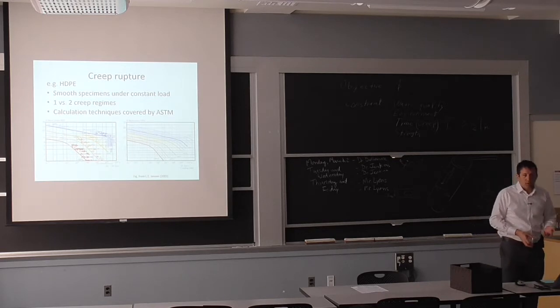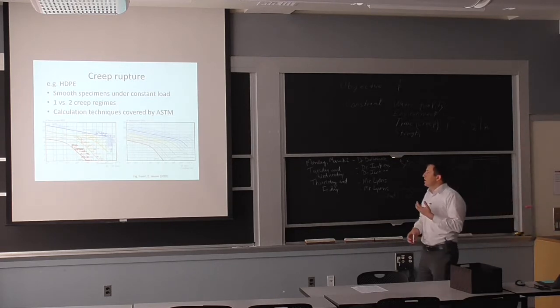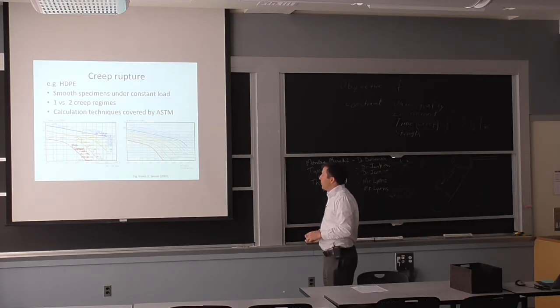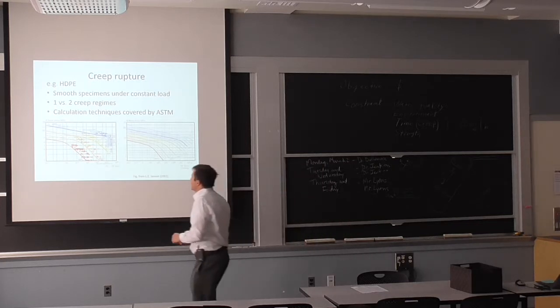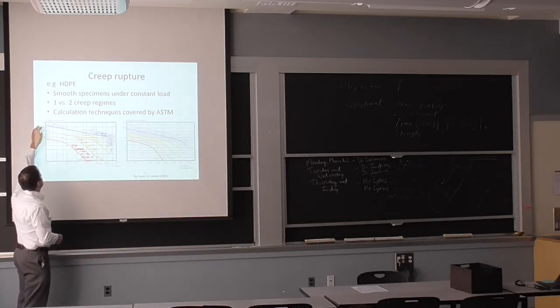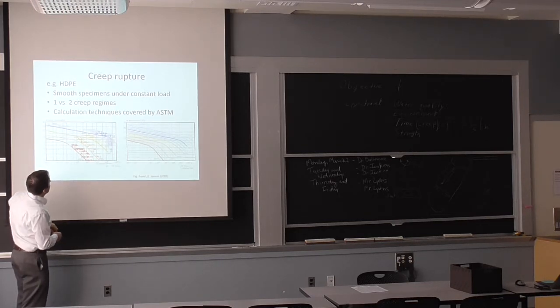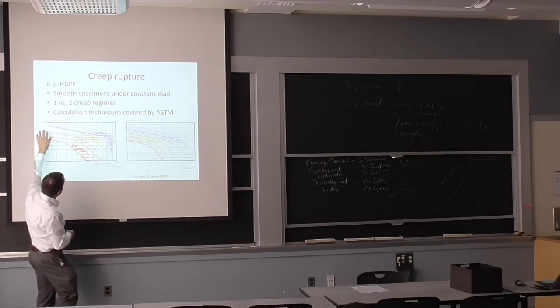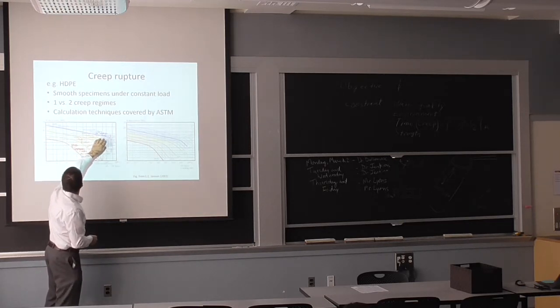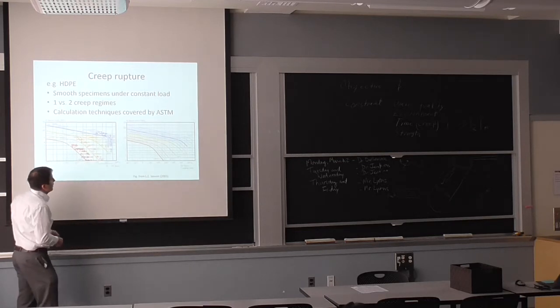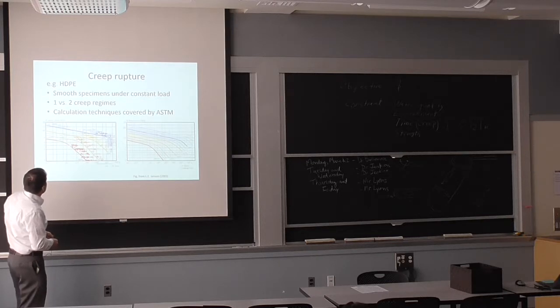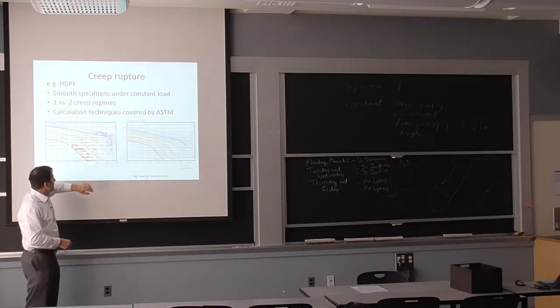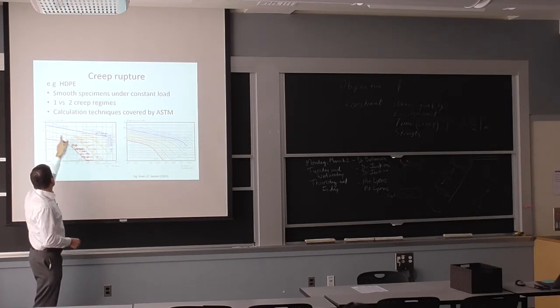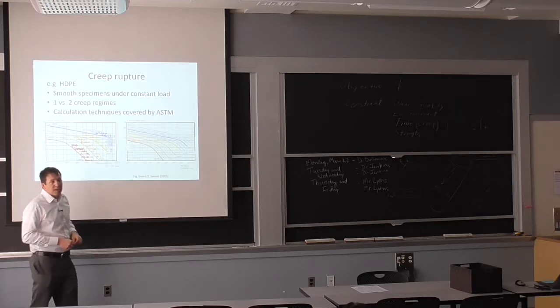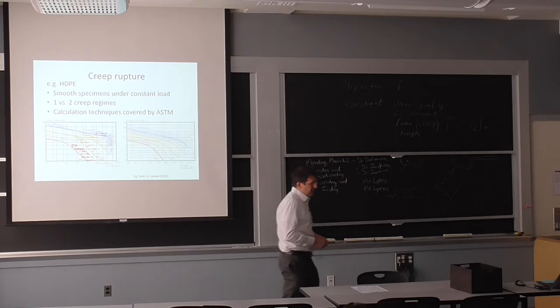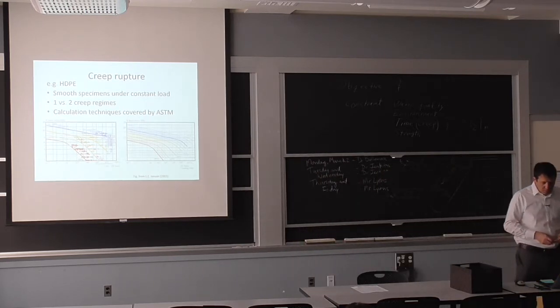So I said we'll use polyethylene a lot for pipes. And I talked about how we're going to reduce the loading. These curves essentially just give you some idea that if your burst stress when you do a test in the lab is of the order of 17 megapascal, depending on the temperature you're at, you're looking at failing somewhere of the order of 5. So you get a big factor here in the service life. And that's going to depend on your temperature. If the pipe may be at a higher temperature, now all of a sudden if you start at 17, you're looking at 4 megapascal for your strength down the road. So these are very, very low values, but we will design for them.